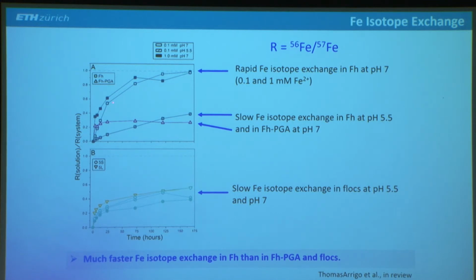The top curves, this is now R over R system, and the top two curves are for pure ferrihydrite at pH 7 at 0.1 and 1 millimolar spiked iron 2. And you can see that they both very rapidly approach a value of 1. So there's a lot of atom exchange going on in the system. If we reduce the pH from 7 to pH 5.5, this is the pure ferrihydrite at pH 5.5, it's much slower. And this is because there's a lot less sorption of iron 2, and therefore it's a much slower process.